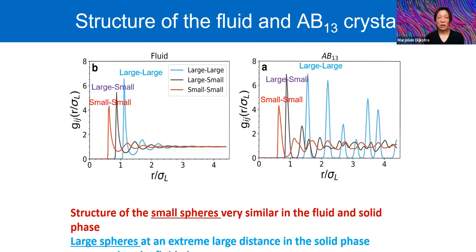If you plot, for instance, the radial distribution function for the small-small, the large-large, and the small-large configurations of a fluid and an AB13 crystal structure, we immediately see that the structural correlations of the small particles are very similar for the fluid and the AB13 crystal structure. For the large-large correlation, we see that the distance where the large particles sit in the crystal phase is really at an extremely large distance, to make room for these icosahedral clusters. And this makes it complicated to define the neighbors of the large particles in the system.